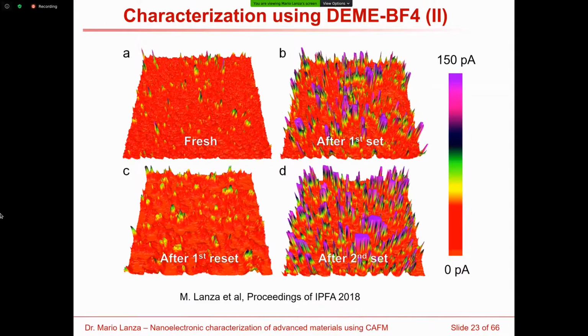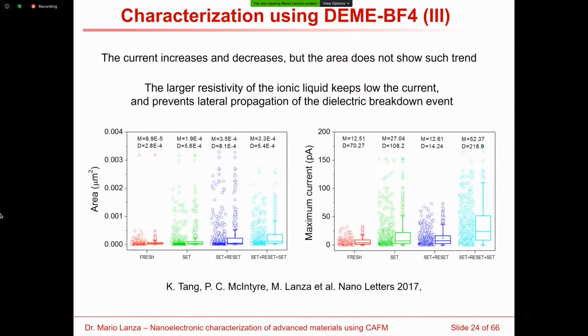Actually, we made some statistical analysis of this area and the maximum current driven by the spots, and it can be clearly seen that the maximum current increases for the set, decreases for the reset, and this is proved statistically because we don't have information about one point or one curve. We have information about multiple conductive filaments, or maybe leaky spots, that we have analyzed with the tip of the conductive AFM.